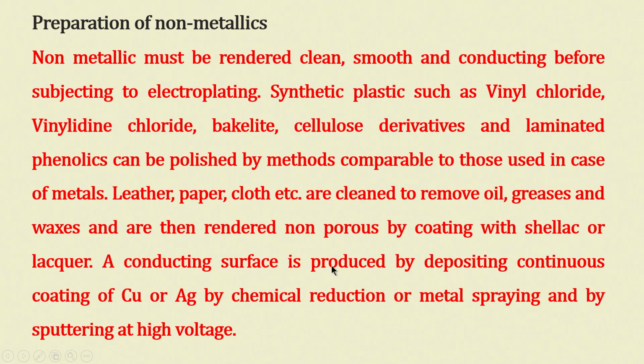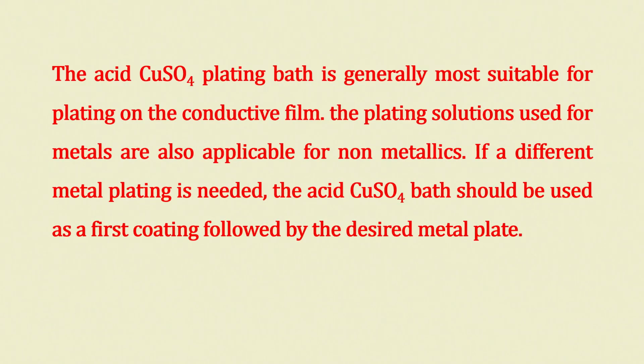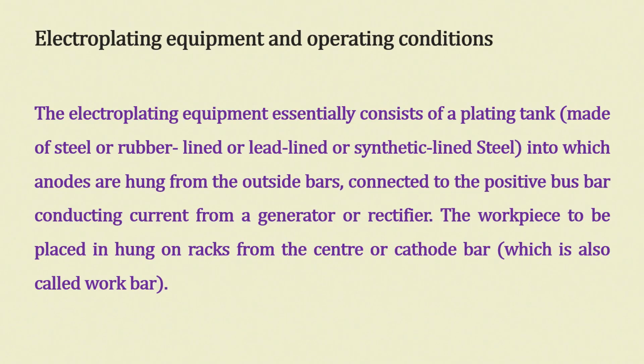A conducting surface is produced by depositing a continuous coating of copper or silver by chemical reduction or metal spraying and by sputtering at high voltage. These are all special technologies that can be employed. So, the acid copper sulphate plating bath is generally most suitable for plating on conductive film. Then plating operations used for metals are also applicable for non-metals. Usually it is the same metal baths, but if a different metal plating is required, then a copper bath should be used first as a coating, followed by the other metal coatings.